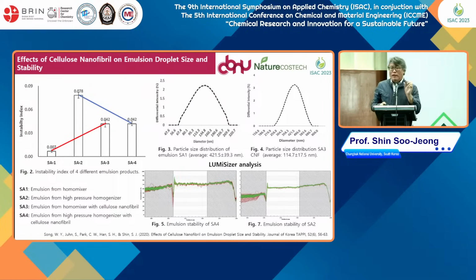Also, when making an emulsion with cellulose nanofibril, it decreases the emulsion size. We made a cosmetic product with cellulose nanofibril, which decreased emulsion size and improved the cosmetic property. The LUMiSizer measurement shows emulsion stability.